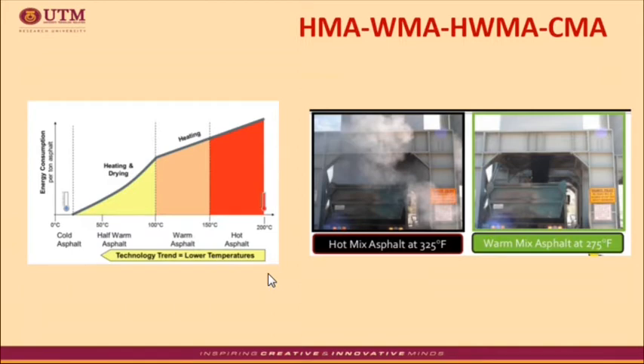As you can see from the figure, if we start to look from the hot mixed asphalt, the mixture is produced and mixed at very high temperatures, roughly between 150 to 190 degrees Celsius. The production temperature of hot mixed asphalt depends on the bitumen used, meaning that the harder the bitumen, the more heat we need to soften it. And then with the new invention of materials and additives, they have come up with warm mixed asphalt, which is produced and mixed at temperatures roughly between 100 to 150 degrees Celsius. And then we have half warm mixed asphalt, which is produced between approximately 70 to 100 degrees Celsius. And finally, the invention of cold mixed asphalt, which is produced with unheated aggregate and bitumen emulsion or foam bitumen.